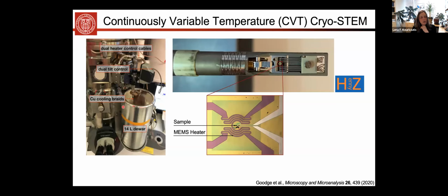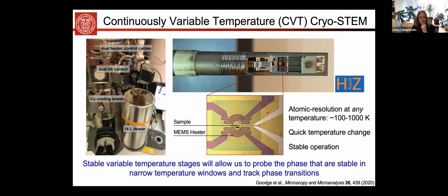But what's so important about this design is that at the tip of the holder, it includes a small MEMS chip. And the MEMS chip allows you to place your sample on it and to locally heat the sample, which then allows you to tune the temperature of the sample while the entire holder sits at liquid nitrogen temperature. Okay, so this is quite important because it allows us to change the temperature very quickly, maintain atomic resolution, and we basically avoid introducing a lot of drift.